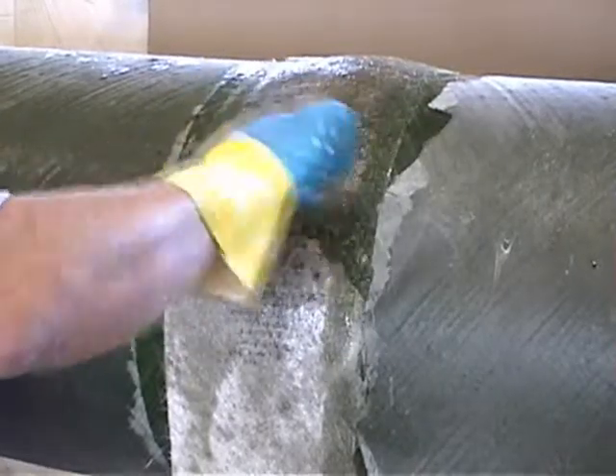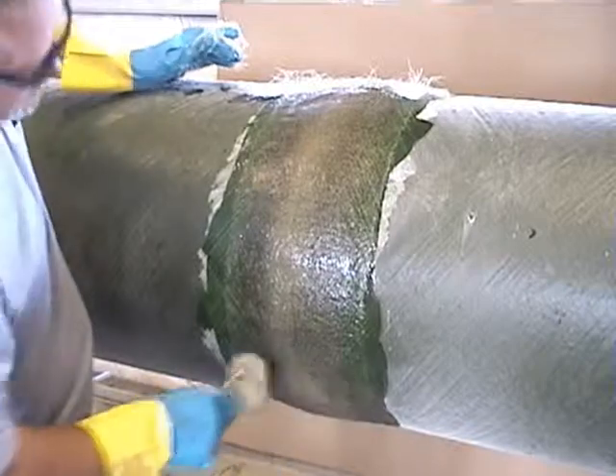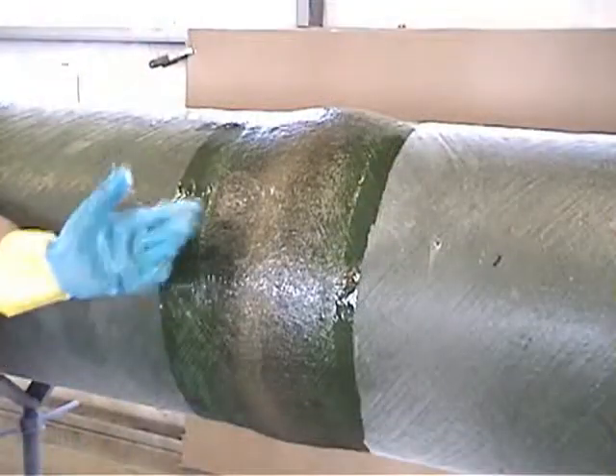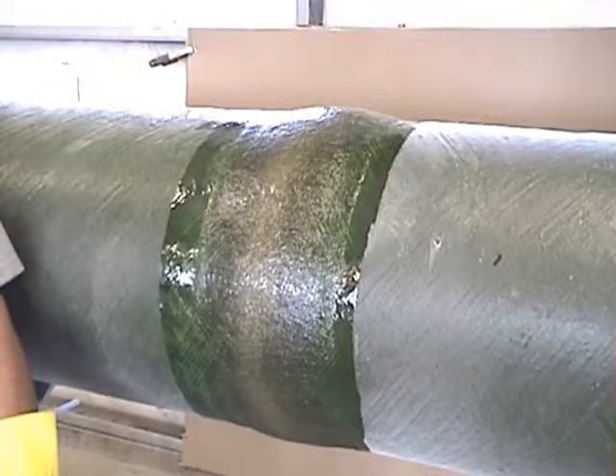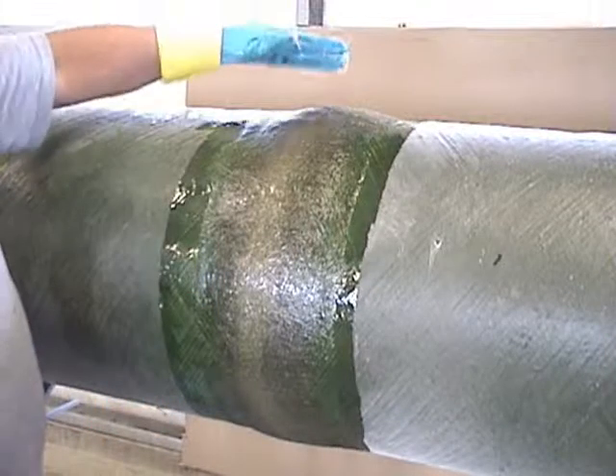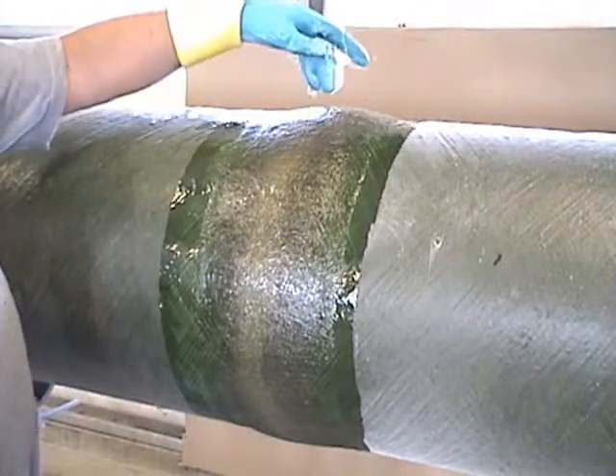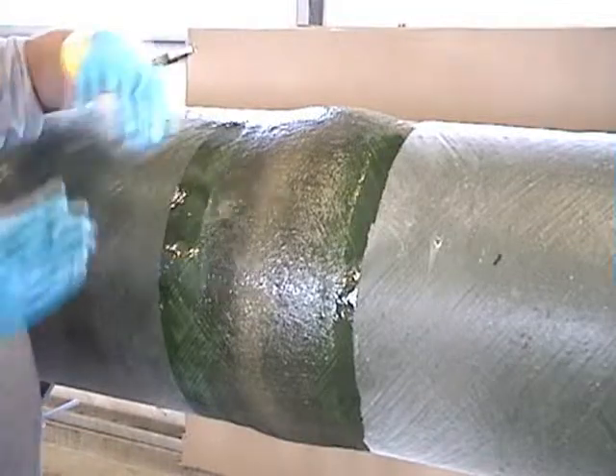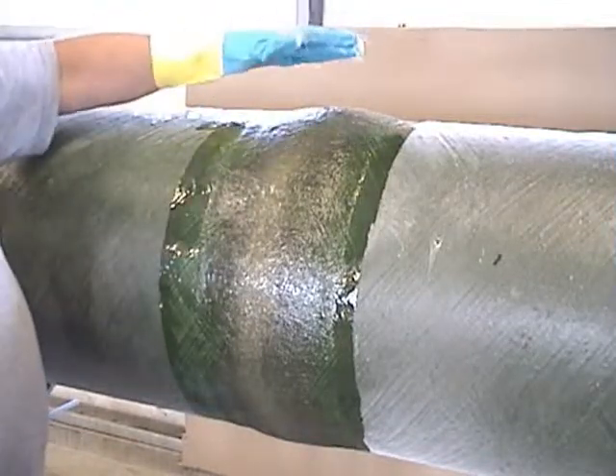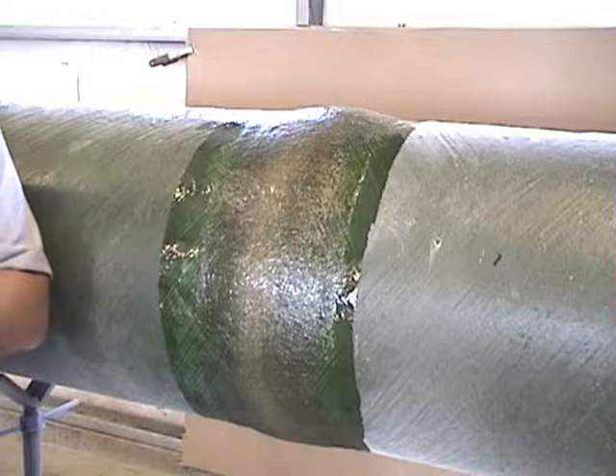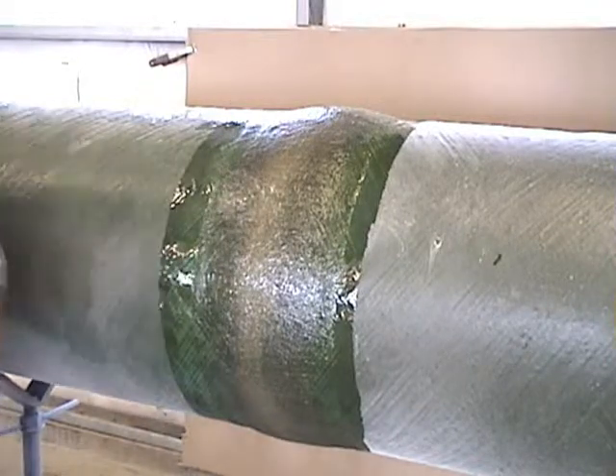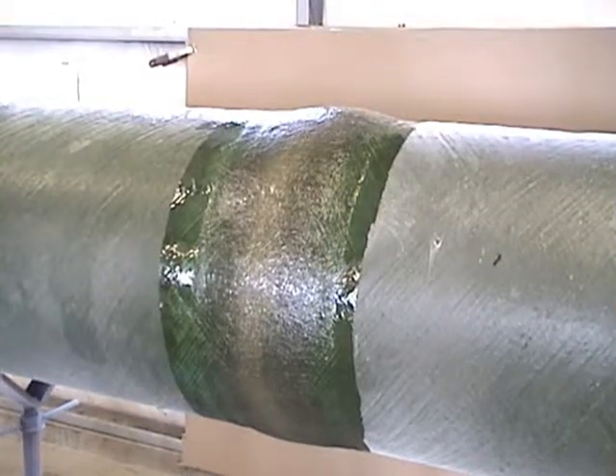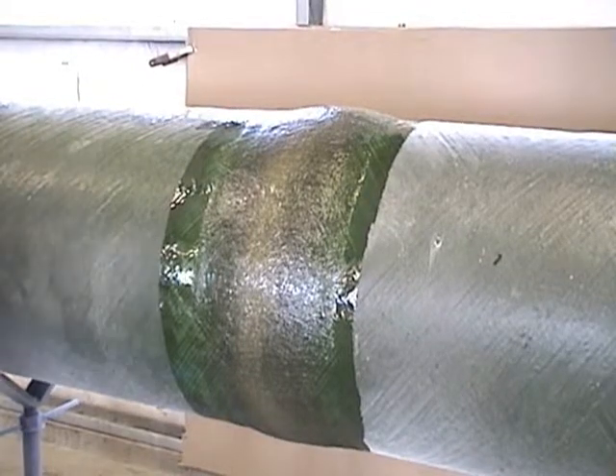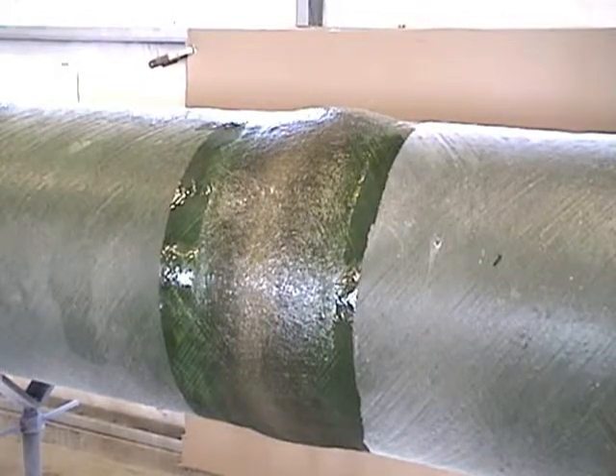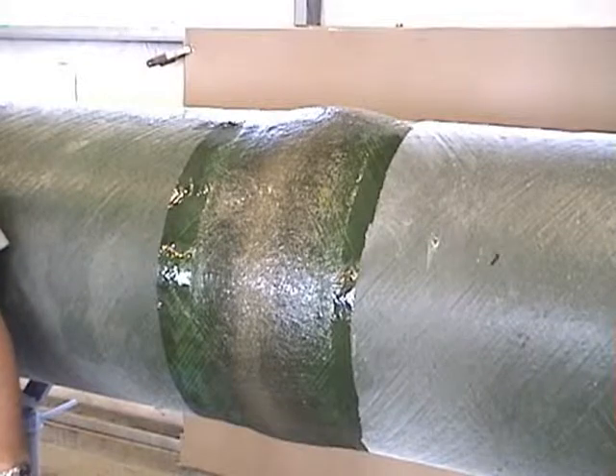Smooth out the resin, removing the air bubbles under it. Once all the air is out of the layup, stop rolling it. You will not use heat to accelerate the cure of the resin. It must cure on its own time to prevent gases from creating air pockets as it cures from the pipe outward. This is how a finished butt wrap should look. We will now let it cure out and get hot, then examine the butt wrap for any kind of delamination. If there is none, we'll apply the cover resin.